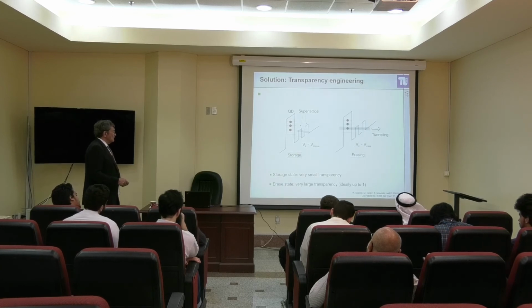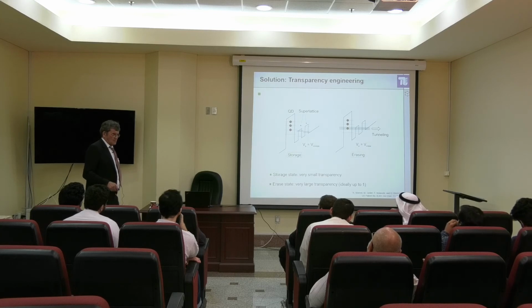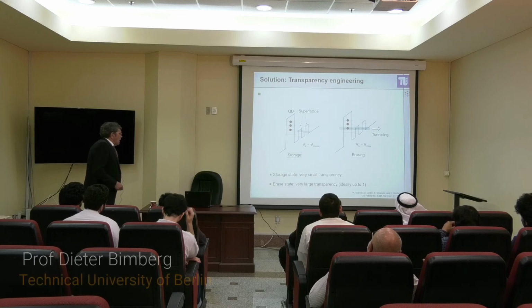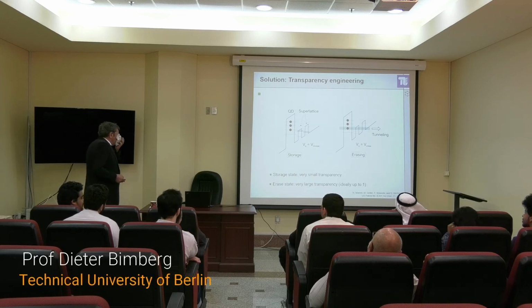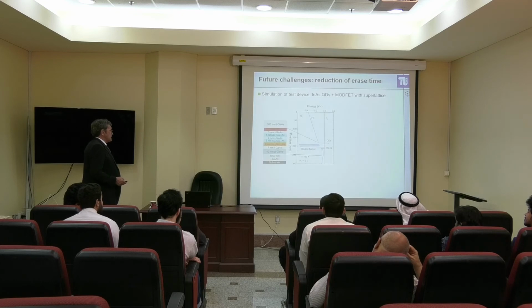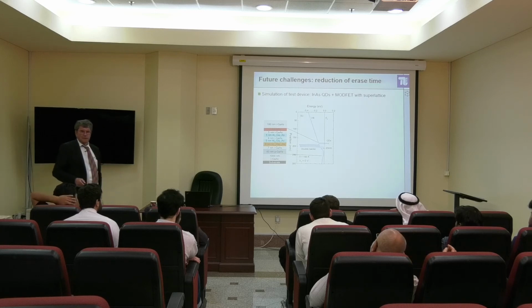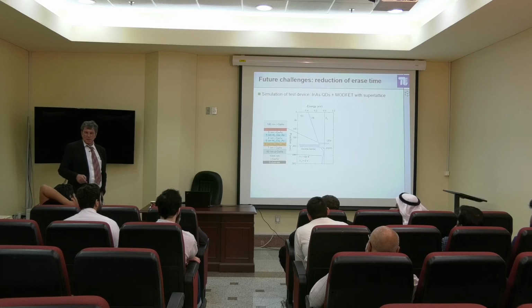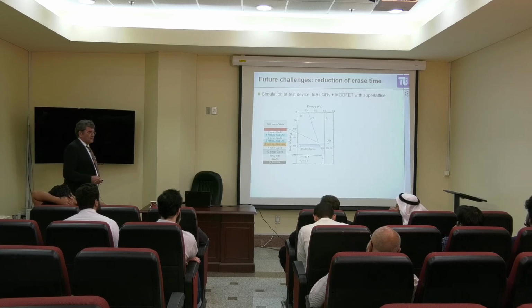Now by changing the bias, you immediately introduce erasing, the tunneling through. And tunneling is in nanoseconds or less. So in the erase state you have a very large transparency. That is actually the matter of a pattern, and that's now his calculation. This is very complex already. You see here many different layers, and doing the calculation is stressful, and he did a lot of theoretical work on the computer.